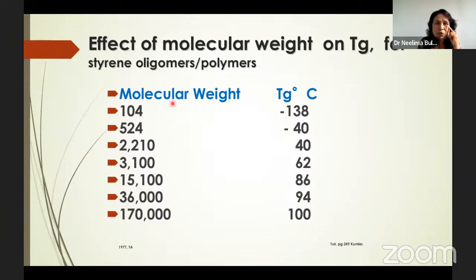Similarly, molecular weight. If you increase the molecular weight, your TG is going to increase. See, for the styrene oligomer, if you increase the molecular weight from 104 to 170 K, TG increases from minus 138 degrees centigrade to 100 degrees centigrade, a difference of around 240 degrees centigrade based on the molecular weight. So if you are synthesizing your sample and getting a different TG, it's a quick way to find out that the molecular weight of your sample is different. Of course, there are different ways you can find it out using GPC and all, but this is a quick, indirect way. Otherwise, you will just use TG to find out the molecular weight. It's not there.